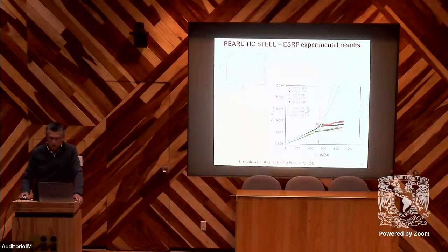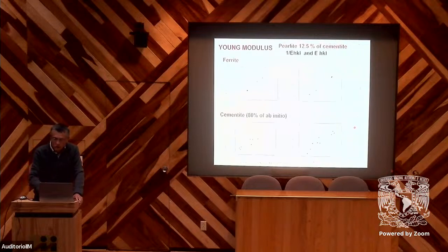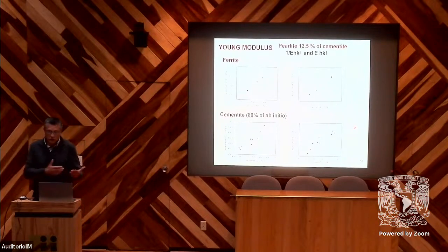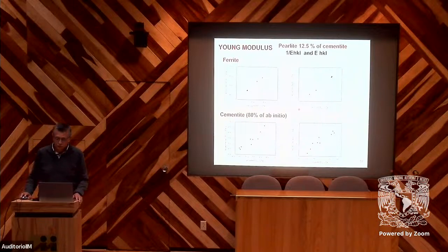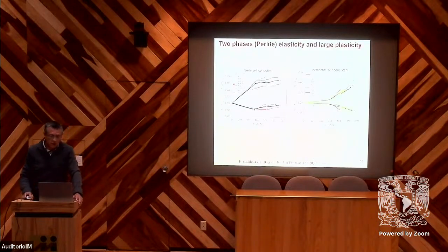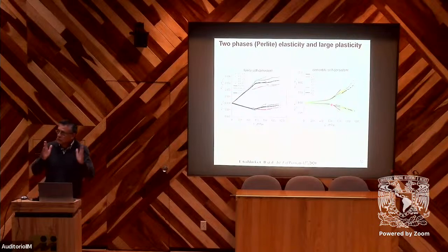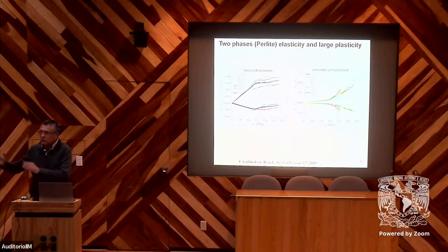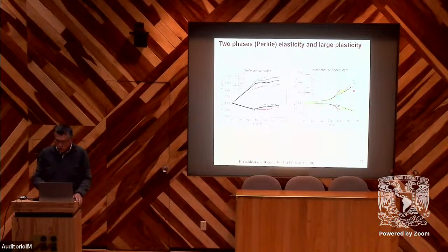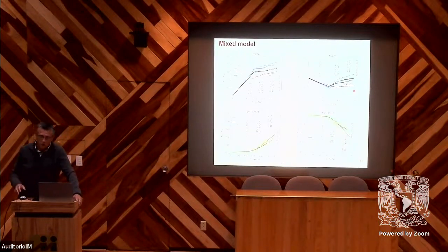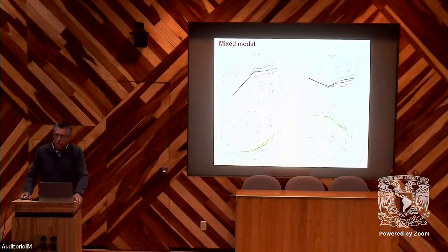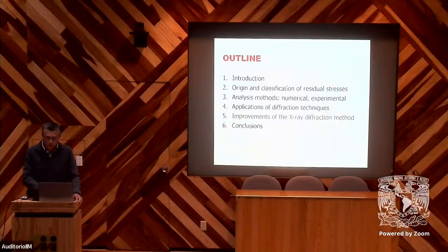And so we can observe here the evolution before the plastic deformation and after. And of course, we can now compare to the self-consistent model, in terms of the elasticity and also in plasticity. We can see here epsilon 11 and epsilon 22 during the tensile test. The problem is that with the self-consistent model, we have good fitting at the range of low deformation, but for higher deformation, we have high differences. So we need to improve our models. For example, here we use the mixed model to have better results. We will continue on this, of course.